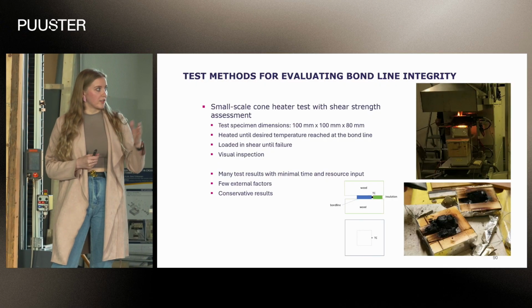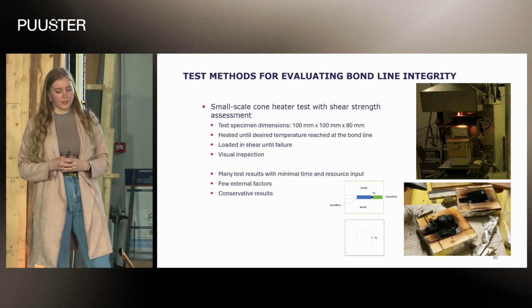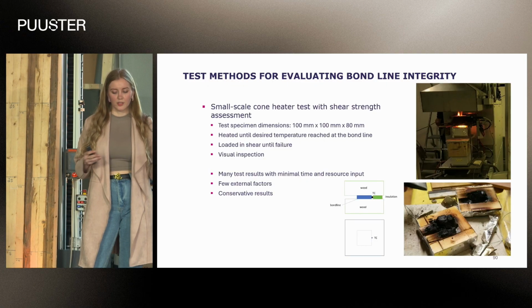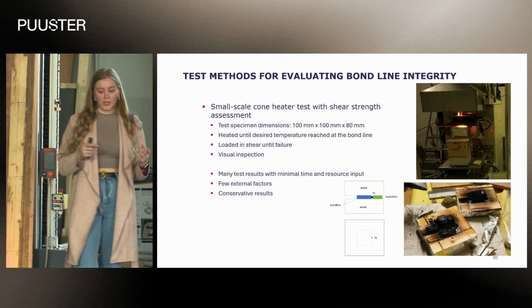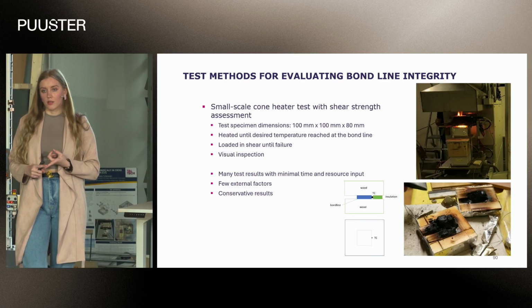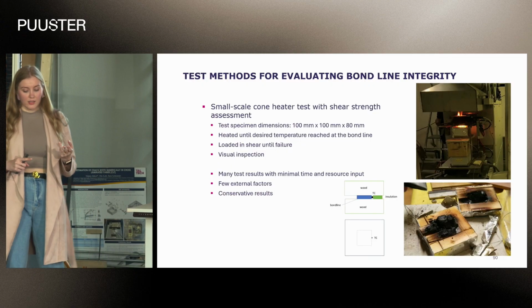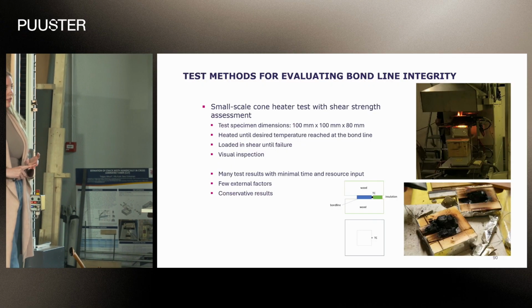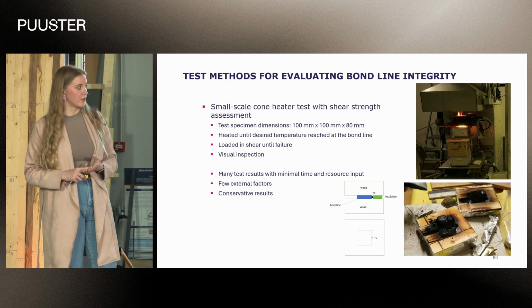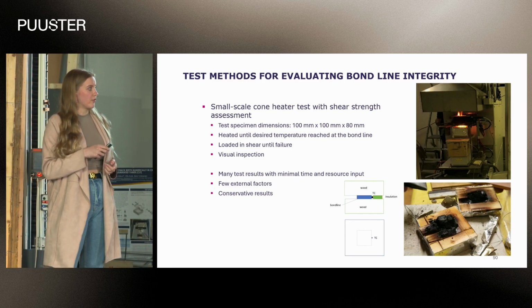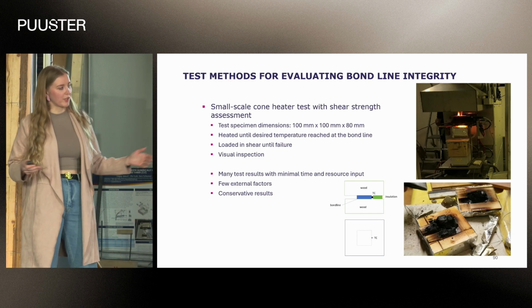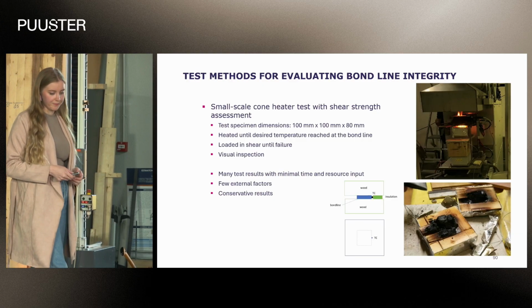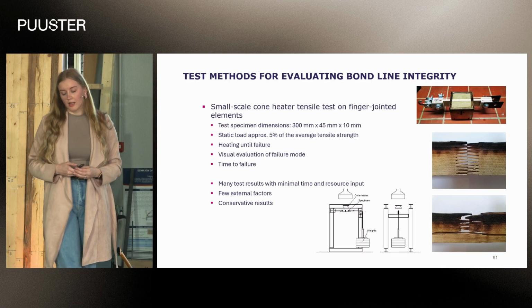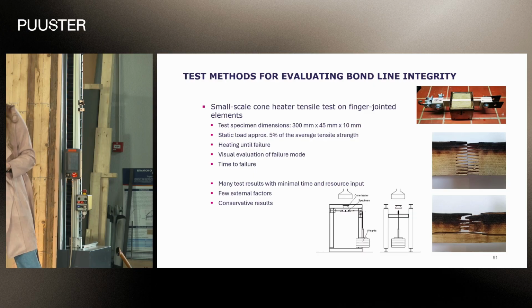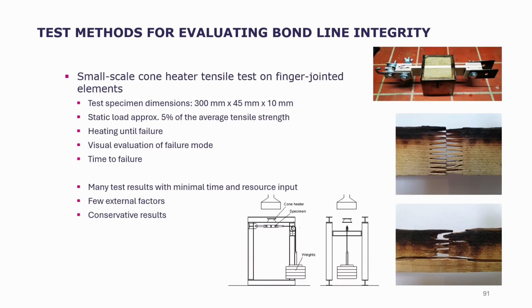And after the temperature is reached, we load it in shear until failure, and we can just compare the shear strengths. We can do many tests in little time with little resources, and there are only a few external factors that influence the results. The results are, however, conservative, which means that we can also apply it very widely. The second method, also developed here at TalTech, is the small-scale cone heater tensile test for finger-jointed elements.